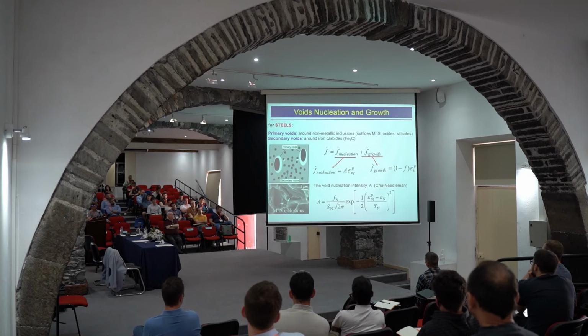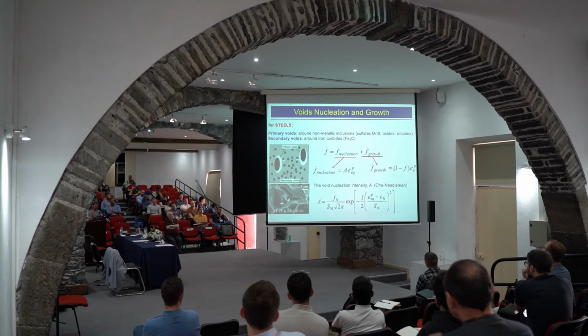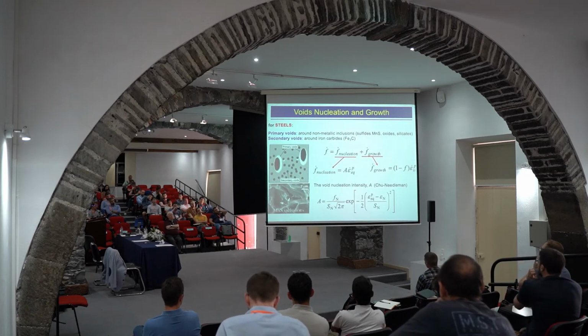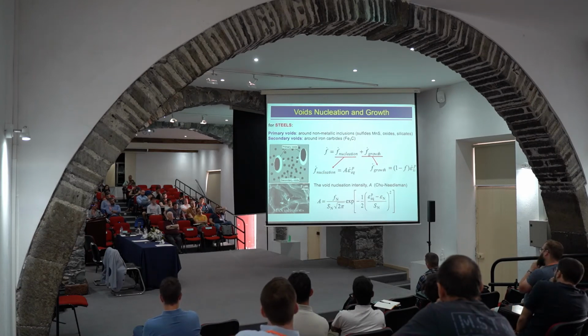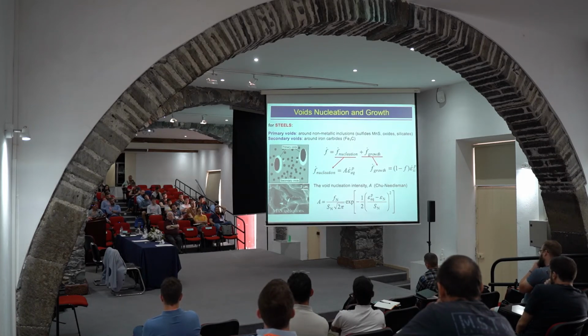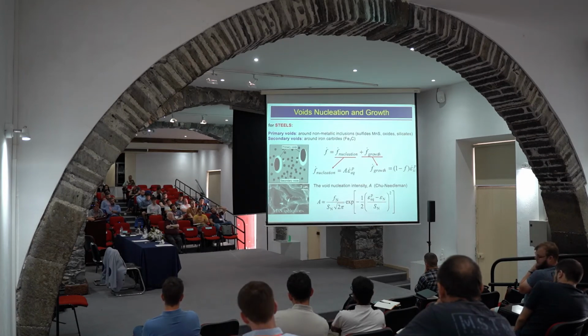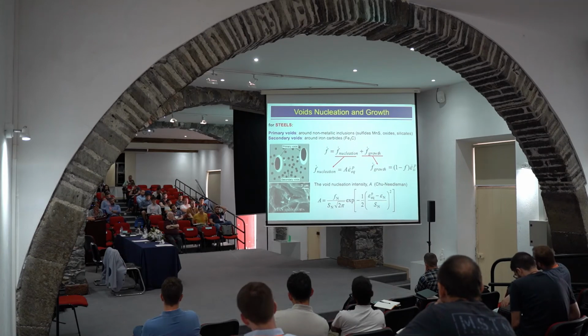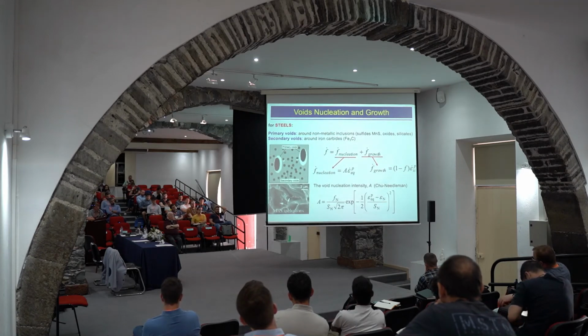So here, the next slide, we can see that volume fraction consists of two parts, nucleation and growth. You can see also some micrographs indicating, once again, these primary or secondary voids, that is also important to distinguish. You can see also this parameter A, defined by Chu and Needleman, with a few material parameters. And just to notice that primary voids form around non-metallic inclusions like sulfides, oxides, silicates, whereas secondary voids, in the case of steel, would form around iron carbides.